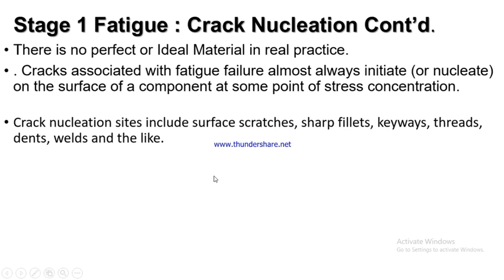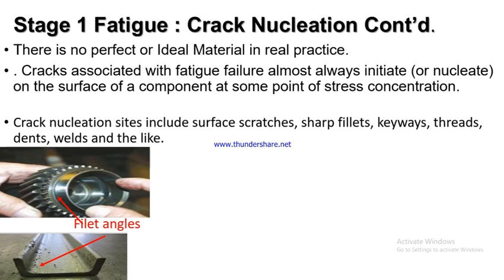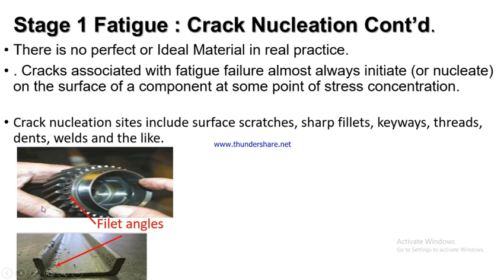Like I said before, we cannot have an ideal material, and sometimes when we try to avert these voids or imperfections in materials during mechanical assemblies, maybe you try to put keyways or fillet systems, they can actually cause stress concentration in the material. Once those stresses are concentrated and the material is subjected to cyclic loading, we found out that the failure will begin to initiate along the stress concentration points of the material.